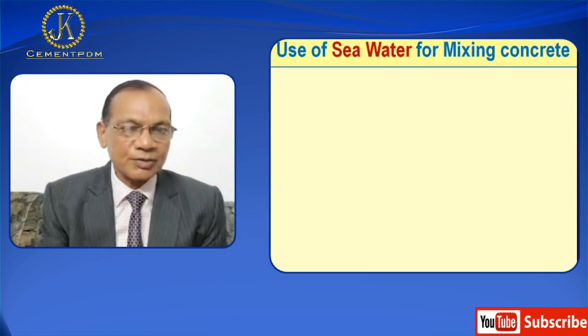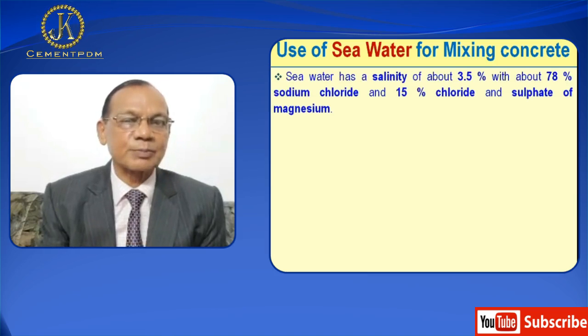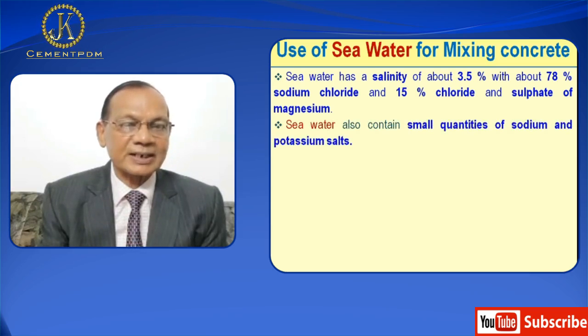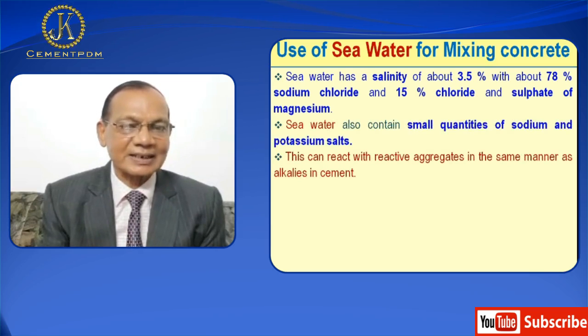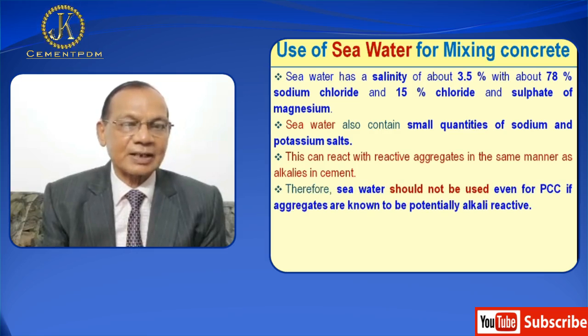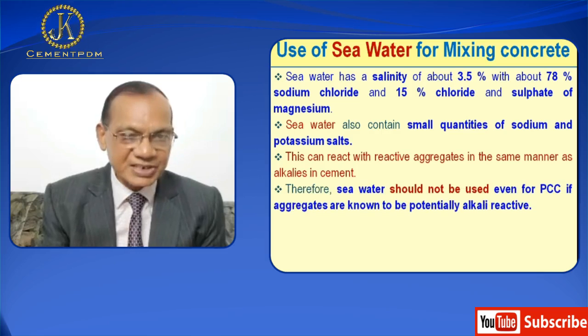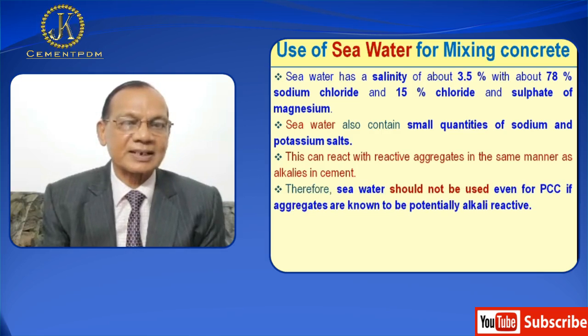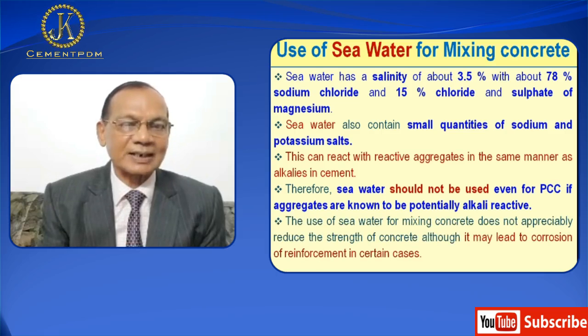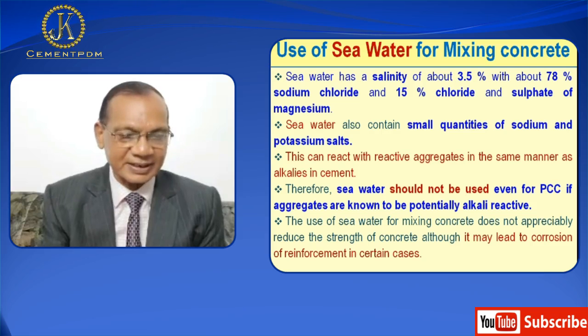Now I will discuss use of seawater for mixing concrete. Seawater has a salinity of about 3.5% with about 78% sodium chloride and 15% chloride and sulfates of magnesium. Seawater also contains small quantities of sodium and potassium salt. This can react with reactive aggregate in the same manner as alkalis in cement. Therefore, seawater should not be used even for PCC if aggregates are known to be potentially alkali reactive. The use of seawater for mixing concrete does not appreciably reduce the strength of concrete, although it may lead to corrosion of reinforcement in certain cases.